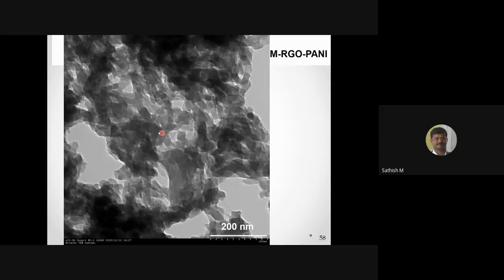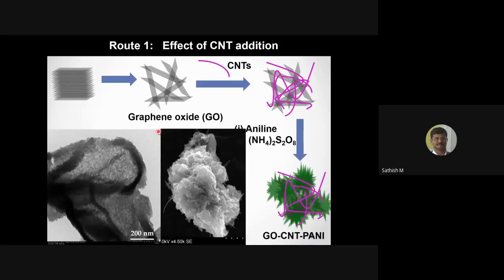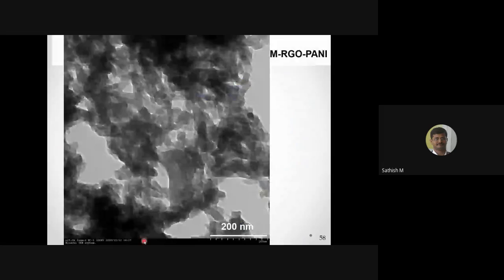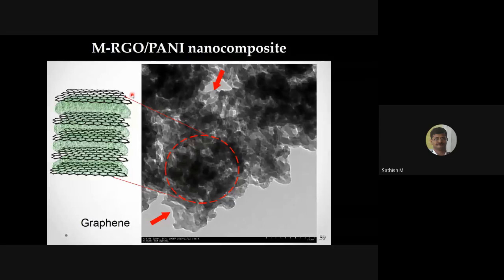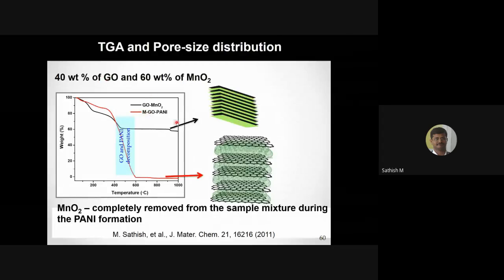You could see it is highly porous in nature. In the previous case, a very thick polymer has been formed, and there is no porosity. Whereas here, it is highly porous in nature. We also confirmed this using TGA. We have seen the graphene manganese oxide has some 60% of manganese oxide. Whereas when you use aniline, the manganese oxide is removed and the polyaniline gets polymerized. For that material, you could see it's almost zero. That means there is no manganese oxide residue in this material. The manganese oxide went completely into the solution.